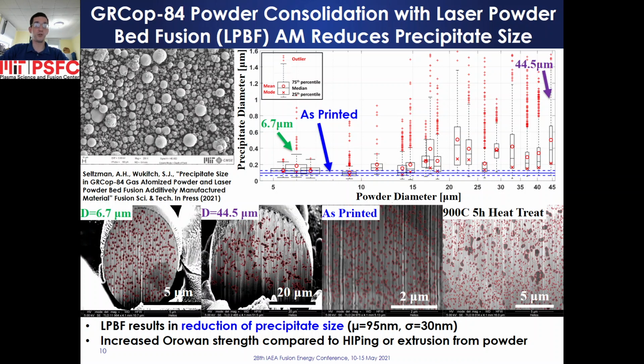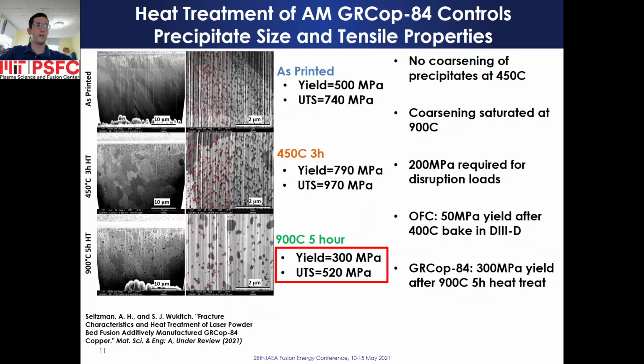As 2/3 of the strength of GRCop-84 comes from precipitates by the Orowan mechanism, the greater number of small precipitates results in a material that is much stronger than can be achieved if the material was consolidated using hot isostatic pressing or extrusion from powder, where the initial precipitate size within the powder stock would be maintained during the consolidation process. Heat treatment of additively manufactured GRCop-84 is used to control precipitate size and tensile properties.